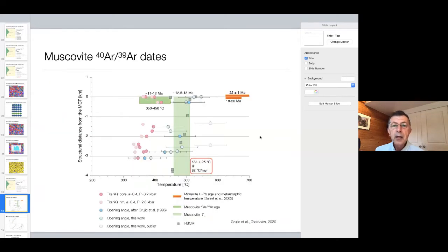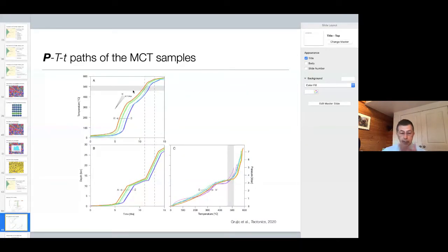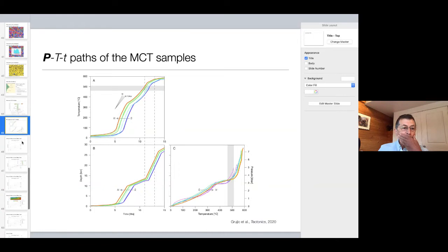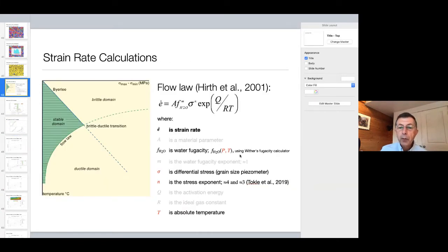And to do that, we again use this diagram, this data, the distribution of the temperature with depth and the thermomechanical modeling of thermochronological data. We obtained these curves. From the modeling, we obtained the temperature evolution with time, which at the same time allows us to calculate the depth with time or pressure with time. So for each temperature and each sample, we can then determine at which depth or at which pressure these samples were at a given time or at a given temperature. And from that, we could then calculate the fugacity. And now we have all the parameters that we need to calculate the strain rate. And the corresponding diagram looks like this.